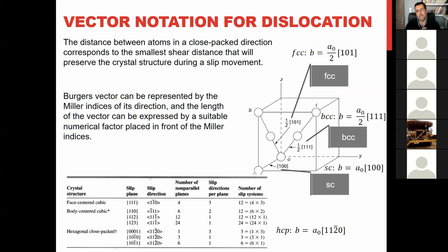And we can show these Burgers vectors by notation of crystallographic directions. Here is a summary of these four important crystal structures in metallic materials, showing the Burgers vectors. For example, FCC. For FCC, do you remember this direction is the close-packed direction. So this direction is the direction of the Burgers vector. And the Burgers vector is the distance between two equivalent positions of atoms, for example from here to here. So the notation for the Burgers vector of dislocation in FCC becomes like this.